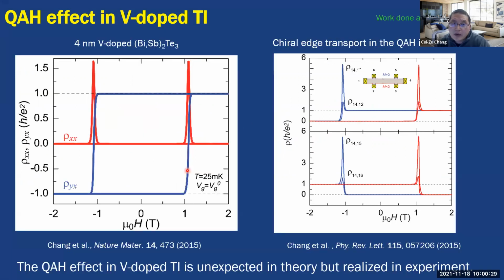And when I graduated from Tsinghua University, I moved to MIT for my postdoc, and I realized a high precision quantum anomalous Hall state in a second system by just changing the magnetic doping, from chromium doping to vanadium doping. Actually, the reason I didn't use vanadium when I was a graduate student is that the DFT calculation said vanadium is not good. But when I was doing the experiment, I found the vanadium-doped TI actually shows the best ferromagnetic property. So that's the reason we chose this one. And finally, we realized a very high precision quantum anomalous Hall state in the vanadium-doped topological insulator system. In this system, at 0 magnetic field, the Hall resistance is fully quantized and the longitudinal resistance is less than 3 ohm.